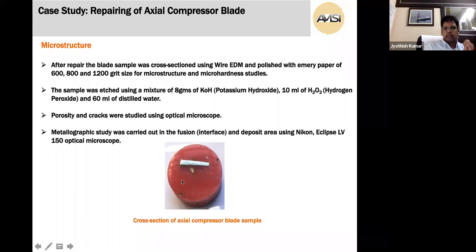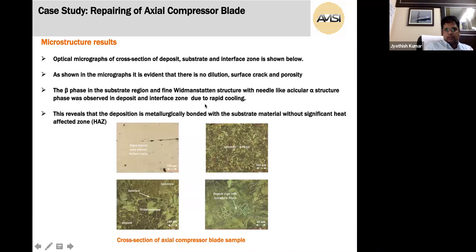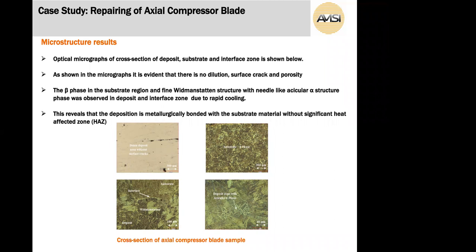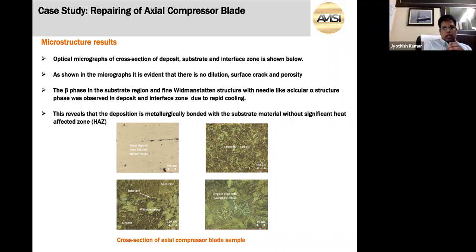This image shows the axial compressor blade which is being sectioned after deposition. Yeah, the microstructure results. Basically, the Ti6Al4V alloy represents a fine Widmanstatten structure, with the acicular alpha phase in the interface zone. When I say interface zone, that is the zone where the deposited material is bonding properly with the base material. If we observe the Widmanstatten structure, that shows that the bonding with the base material is very good, which also reveals that the metallurgical bonding with the substrate material is very good, and there is less heat affected zone.